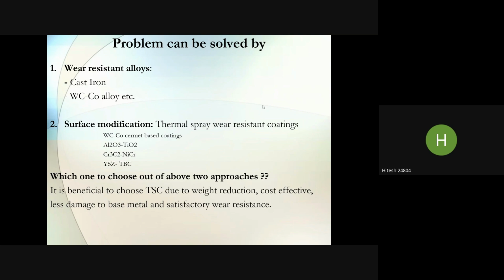Then these are the materials which can be used, like for wear resistance applications, where there is direct contact of the materials with each other. So tungsten carbide cobalt is the material which is used for room temperature applications. Their extended versions are already there: tungsten carbide cobalt chromium. Then you can further integrate this particular process with laser texturing. So you can perform laser texturing on the surface, and then you can use this particular material on the surface.